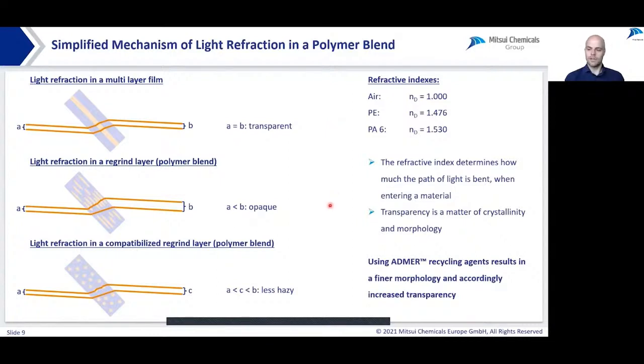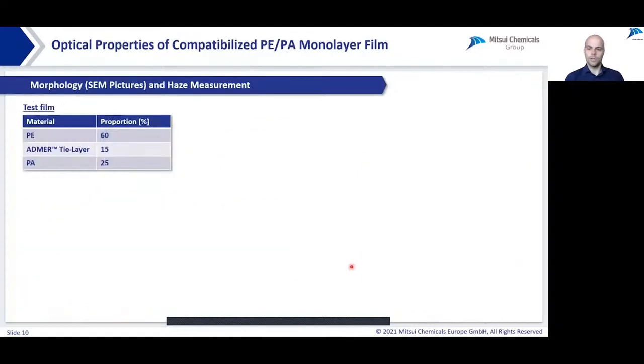Using ADMER recycling agents results in a finer, more homogeneous morphology. An optimized morphology is responsible for a higher transparency and an improvement of crystallinity during the cooling step of the production. To show you how it looks like in real, we took some SEM pictures.